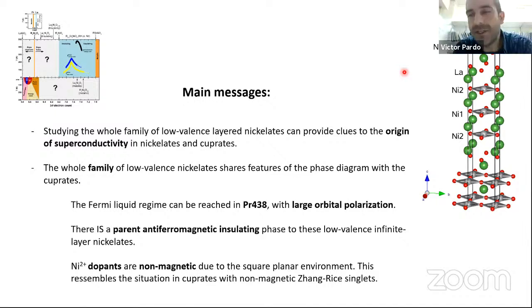Yeah, I mean, certainly the oxygen p bands would be much farther away from the Fermi level than in the cuprates. So we know that. But the thing is that it's crucially different to the bulk, so the main idea of that calculation is that the antiferromagnetic insulating phase of the nickelates exists. You just need to add an additional ingredient, and that helps you understand where that hugely dispersive band comes from, because there's some discussion as if that band is really neodymium, is it really nickel?